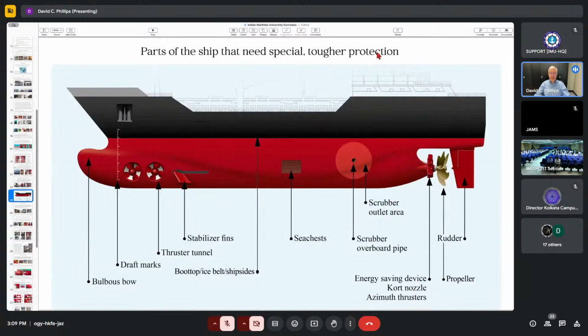The parts of the ship that need this special kind of protection include the bulbous bow. For many kinds of ships, particularly if you're sailing in ice or something like that, the bulbous bow suffers badly. The draft marks sound like a detail, but it's really important to have draft marks that you can see. And the coating tends to be taken away on regular coatings. Inside the thruster tunnels, we've talked about already, there's an area that's very subject to cavitation. Stabilizer fins, if you've got them. Sea chests, the grating and so on, it can easily lose its coating.